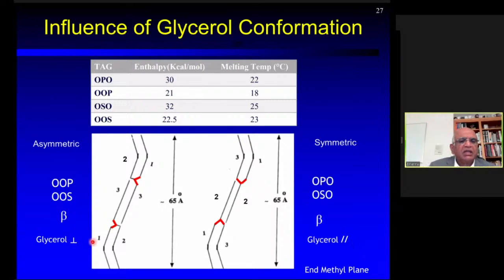This has an implication in real systems like the phospholipids, where the polar function which is attached at the 3 position of the phospholipids goes up in the bilayers, and with the 2 acyl chains in the bilayer takes this glycerol perpendicular orientation. That is the implication that we can show, that this has a relevance to the natural systems.